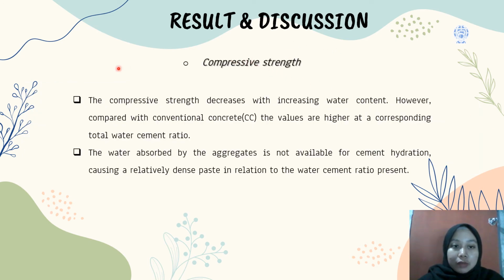The compressive strength result is that it decreases with increasing water content. However, compared with conventional concrete, which is CC, the values are higher at the corresponding total water cement ratio. The water absorbed by the aggregates is not available for cement hydration, causing relatively dense paste in relation to the water-cement ratio present.